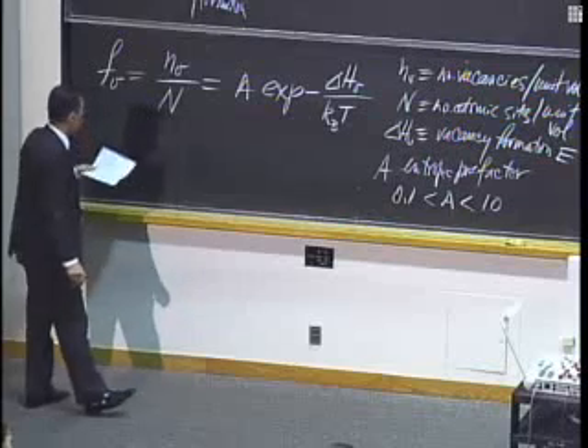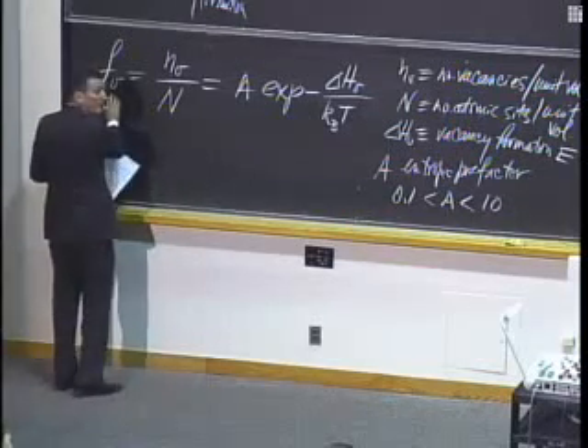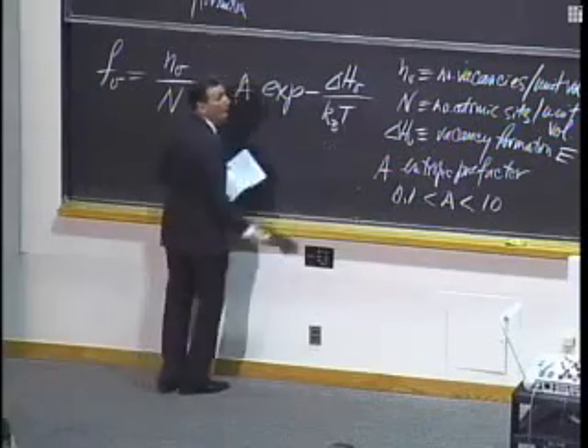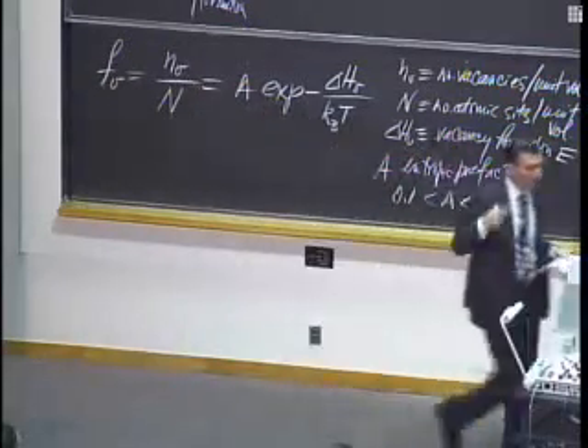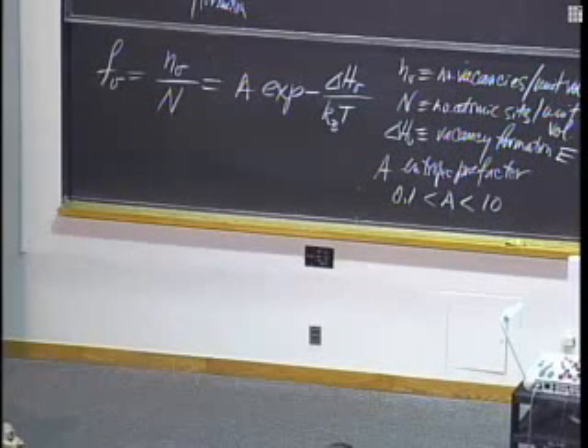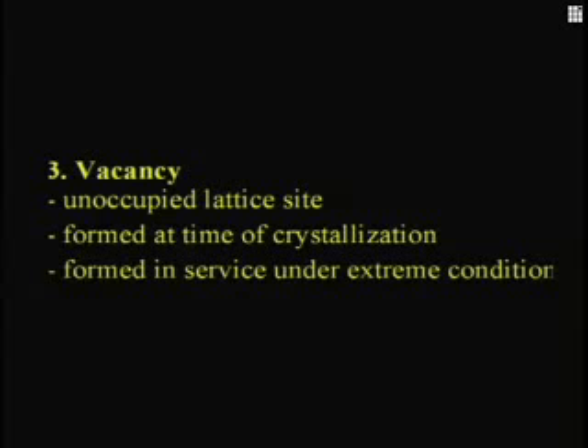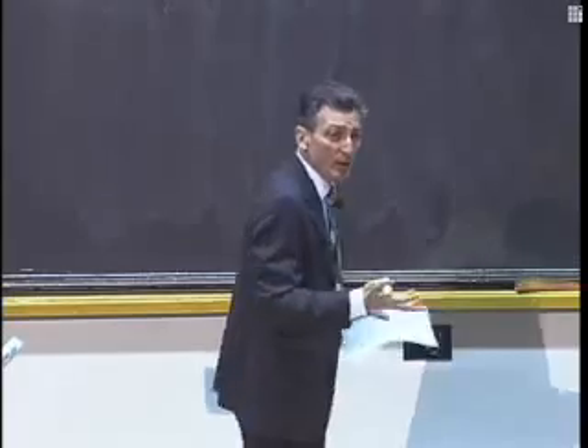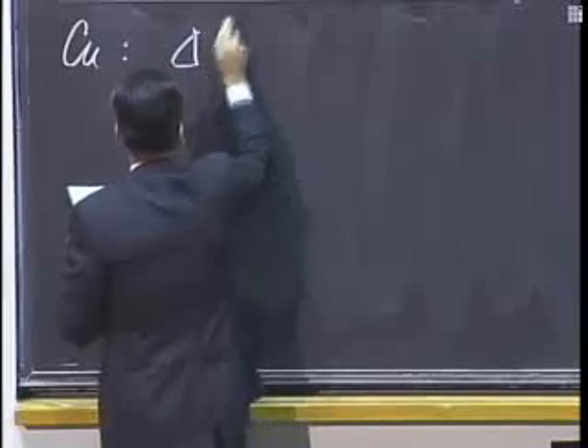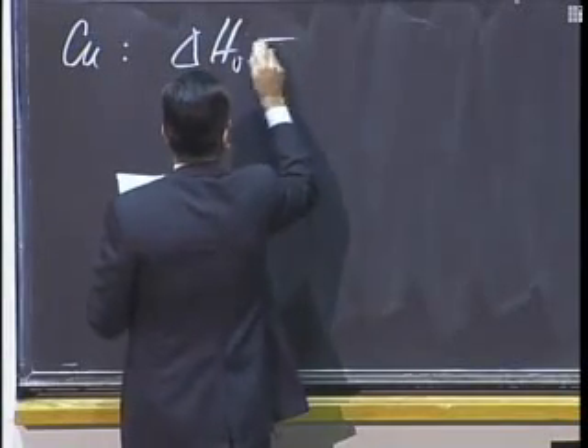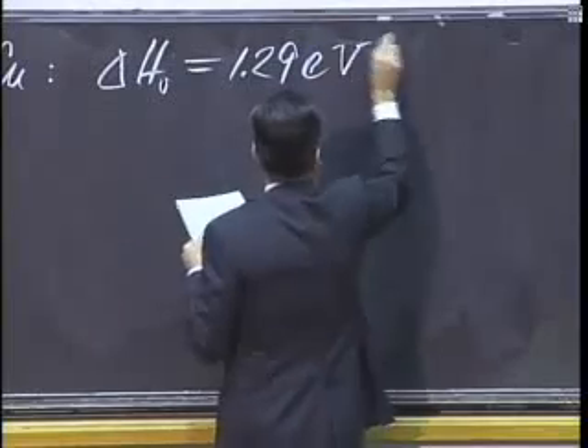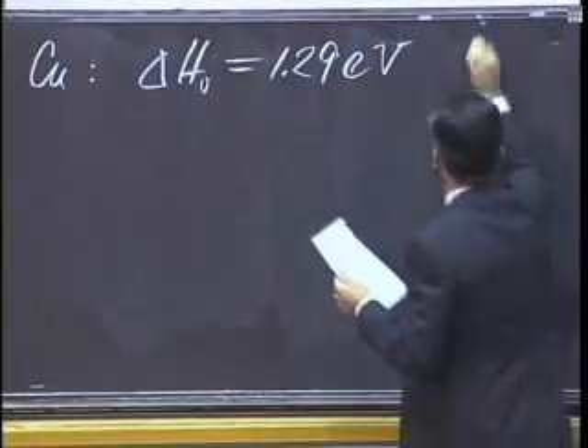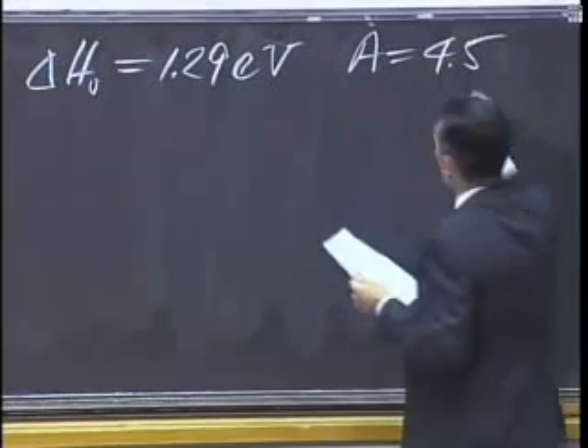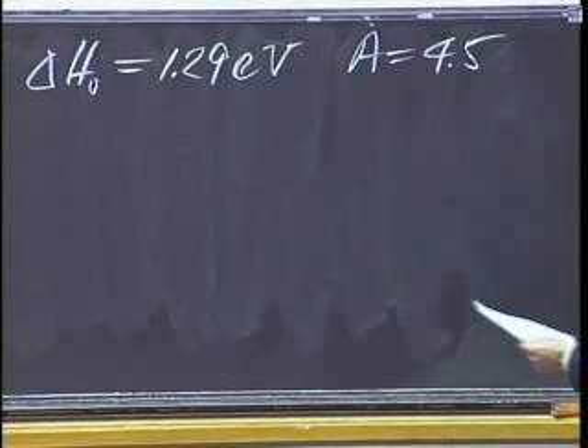less than 1. So this is a relationship that tells us what the fraction of unoccupied sites is as a function of temperature. So we could go in and calculate what the effective bond energy is, because we know what the thermal energy is, so we could work backwards and calculate that. So I did a sample calculation. I was wondering, what should be the vacancy population in, say, a piece of copper? So I said, all right, copper happens that the enthalpy of formation of a vacancy is 1.29 electron volts per atom, and the prefactor is equal to 4.5. I had to look this up in tables. This is not from first principles calculations.